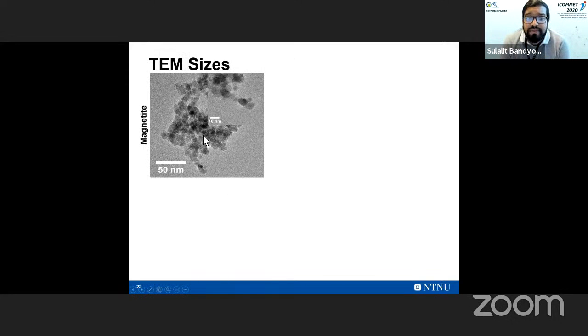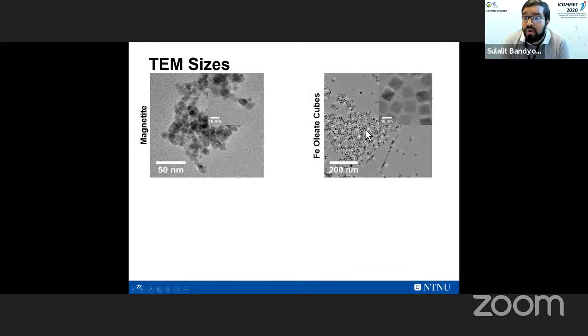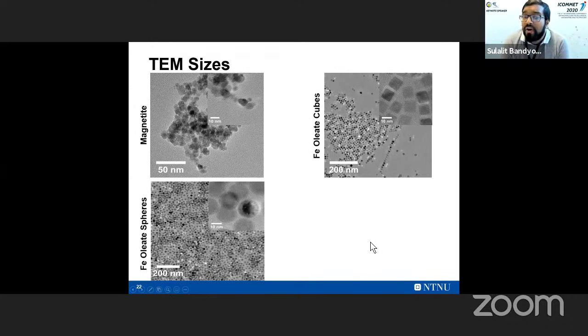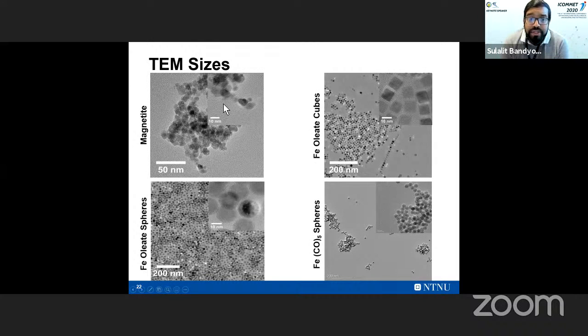So this is a typical image of the magnetite. When you look at the cubes, they look like this: the iron oleate cubes, the iron oleate spheres, and the iron pentacarbonyl spheres. These are all TEM images, and they show that with magnetite, you always get aggregated particles if you don't use a stabilizer, as in the co-precipitation method. Whereas in thermal decomposition, you get very nice size distributions.